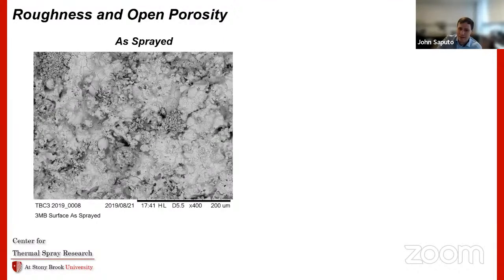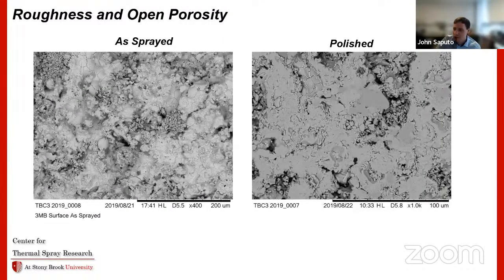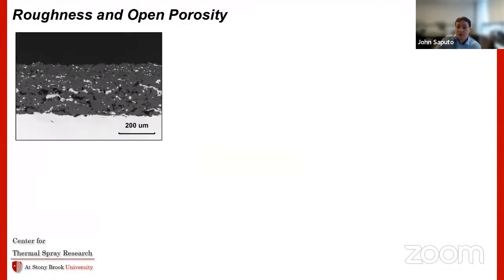They're totally chaotic and have all these really small scale features. So as you polish it out, you can see this, and you still do see pits on the surface that we thought may have some interaction with the combustion process. So to get rid of this, we decided, hey, we can just tune our process variables, spray a dense thin coating on top of that, and seal all of that up.